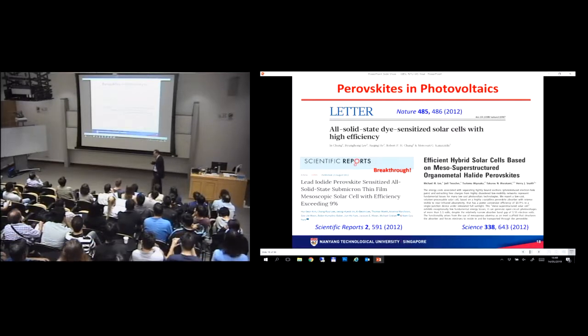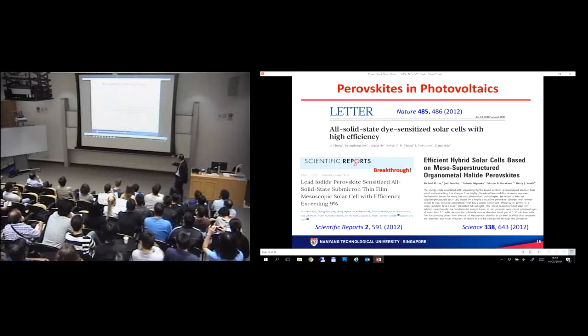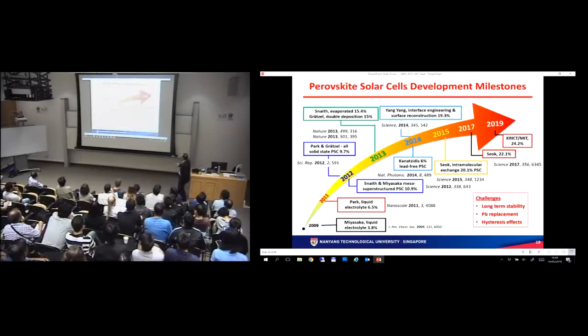Now, the first breakthrough came from Grätzel and Nam-Gyu Park's work, published in Scientific Reports, where they made an all-solid-state perovskite cell, where the perovskite is actually used as the absorber itself, and it got about 9.7% efficiency. Now, Henry Snaith and Miyasaka joined forces, and they came out with a paper around the same time on meso-superstructured nanostructures. That gives about 10.7% efficiency, 10.9% efficiency, sorry.